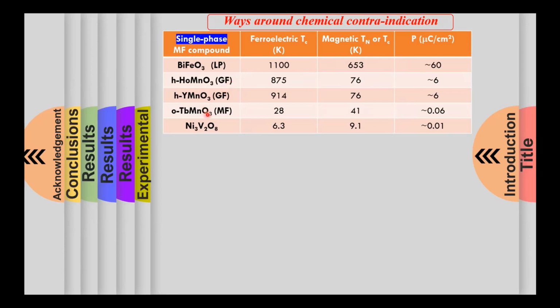In another class of single-phase multiferroics, like the orthorhombic rare earth manganites, for example, the terbium manganites, the ferroelectricity is driven by magnetism. Basically, a non-centrosymmetric magnetic ordering induces polarization in such classes of material. And this kind of ferroelectricity is called magnetic ferroelectricity or spin-driven ferroelectricity. Though the polarization value is pretty low in this class of single-phase multiferroics, they exhibit strong coupling.